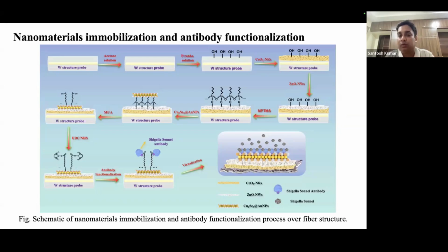After that, for the gold nanoparticles, we need to follow a specific process: firstly we coat the MPTMS. MPTMS is a reagent which can work as an adhesive to attach the gold nanoparticles, because MPTMS adds the SH group over the sensor structure. After that we dip the MPTMS-coated fiber into the gold nanoparticle solution for 48 hours, and the gold particles attach over the fiber structure. After that we wash with ethanol and nitrogen gas so that unbound nanoparticles are removed. This is the nanoparticle immobilization process we follow.